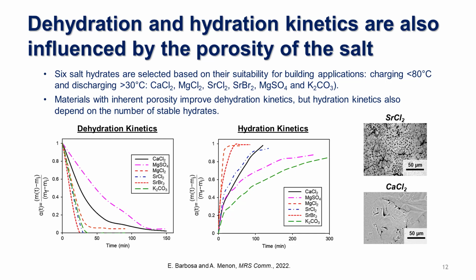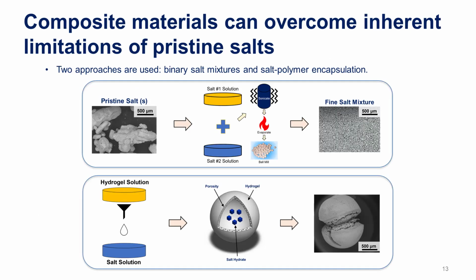And a lot of that, again, is tied to the fact that some of these salts have this nice porous structure, whereas some other salts do not. And when we look at the hydration, now we're providing moisture and the salt starts off in the dehydrated state, picks up the moisture and goes up all the way to its fully hydrated state, 1. Again, you can see that some of these salts like strontium bromide tend to pick up that moisture very quickly, whereas some of these other ones, again the magnesium sulfate and this potassium carbonate, are very sluggish in terms of how much moisture they pick up.